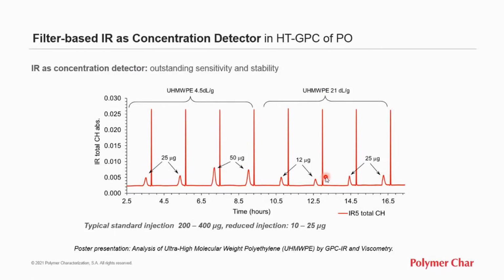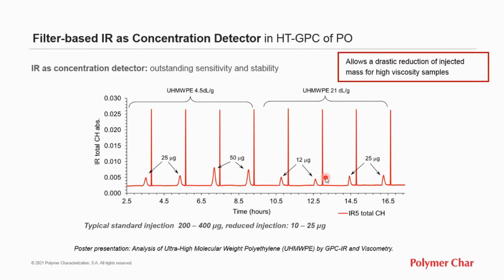One quite challenging application is that of ultra-high molecular weight polyethylene. The high sensitivity and stability of infrared detection allows a drastic reduction of the injected mass, which is required when dealing with such high viscosity solutions. Here in this example, we injected 10 to 20 times lower mass than in standard GPC analysis, and still the signals, the peaks we obtained were good enough.